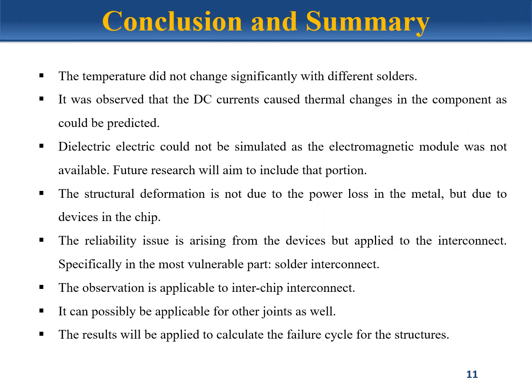So even though the project is not completed, we can form some reasonable conclusions based on the data that we have already received. The first conclusion that we can make is that the temperature did not change significantly with the different solder compositions. We can see this in the simulation data. We can see that as the current rises in the structure, the heat also rises, but with different solder compositions, the heat difference is very minute.